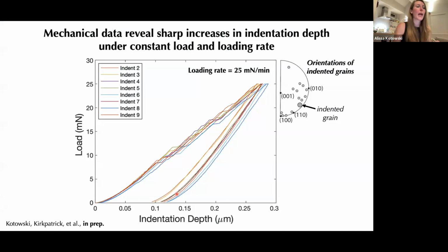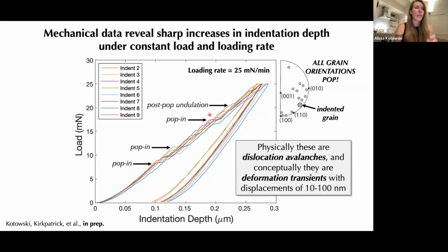So this is what the mechanical data look like. We have indentation depth on the x-axis, and applied load on the y-axis. So for each experiment, we select a maximum load and assign a constant loading rate. And during the loading portion of the experiment, you can see these abrupt increases in indentation depth at constant applied load. These are called pop-ins. And physically, these are bursts or avalanches of dislocations, and they glide suddenly after overstressing the crystal. Basically, these are delayed activation of dislocation sources.